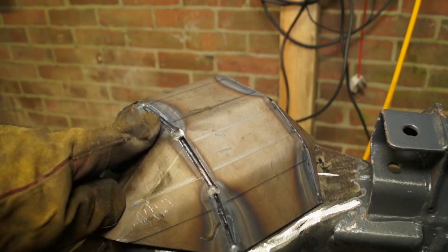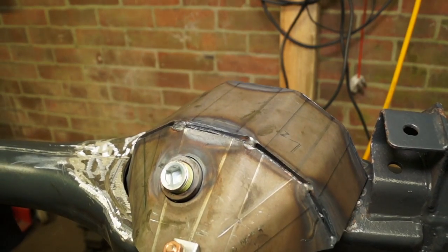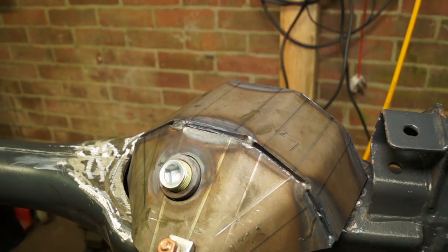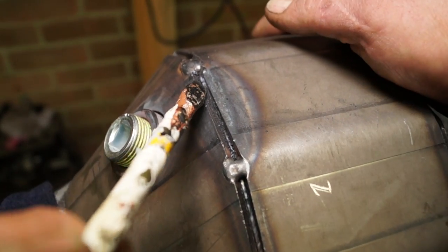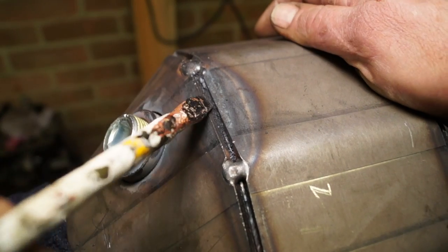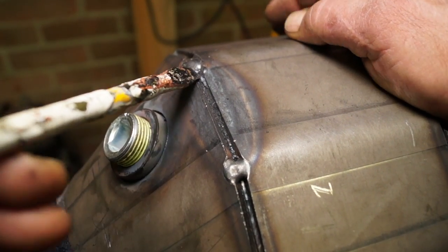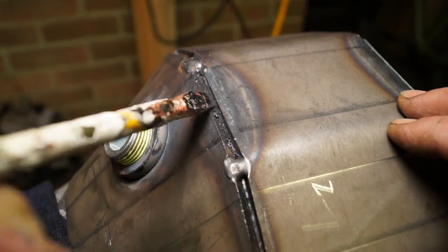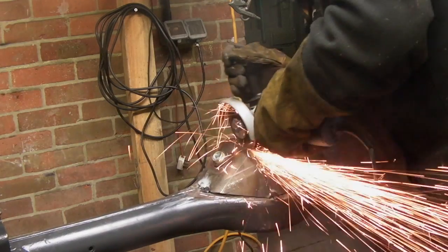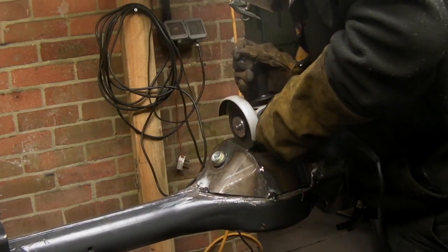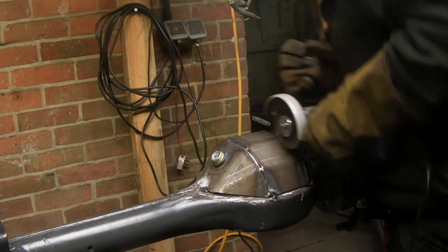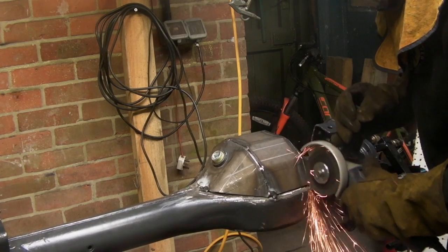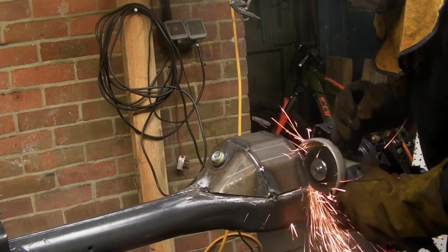Anyway, you can see how much it has penetrated through, and there will be a slag in the grooves here, and I'll just show you this. You'll need to grind them out. Now you can see why I welded the inside first to the outside. So I'm using the cut disc here first of all, and that will clean out the slag. The worst thing you can have is slag underneath your weld.